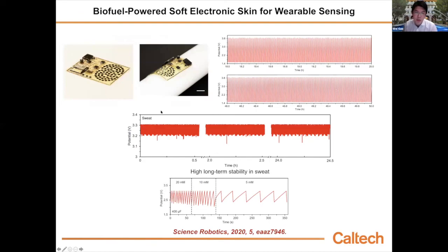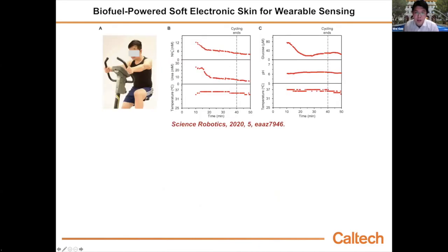We showed that this biofuel cell system is very stable. We can continuously charge and discharge for 50 hours, and you see nearly the same performance. Even in raw sweat, we showed 24-hour performance, still very stable. Taking advantage of this battery-free wearable system, we can continuously track metabolic information. Again, it's very important to monitor our nutritional status to minimize the chance of COVID-19 infection. You see all the risk markers, the urea, ammonia, glucose, pH, we can continuously track